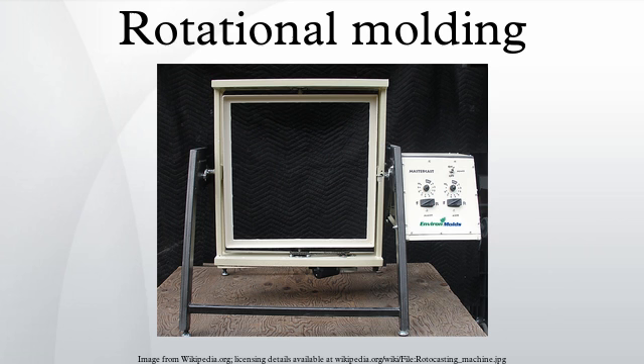The most promising area is in mold pressurization. It is well known that applying a small amount of pressure internally to the mold at the correct point in the heating phase accelerates coalescence of the polymer particles during the melting, producing a part with fewer bubbles in less time than at atmospheric pressure.